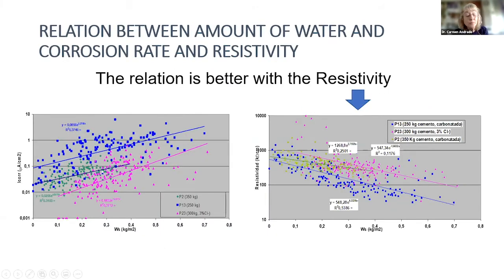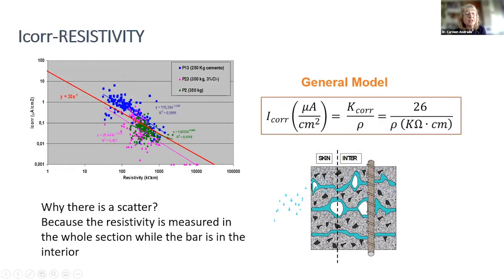And well, we tried to plot the relation between corrosion rate and amount of water inside, and there are trends with a normal scatter, because there are different temperatures, and also differences between the skin and the interior. And the resistivity is the opposite. I mean, the resistivity decreases, of course, when you increase the amount of water inside the concrete. And with these values, we plotted again our graph of corrosion rate versus resistivity, and we found that the trend is clear, although there is a big scatter. And of course, if the steel is passive, I mean, it's not in active condition, this is much more flat, because the corrosion rate does not go above 0.1. In that case, this is clear for active corrosion, but not for passive state.